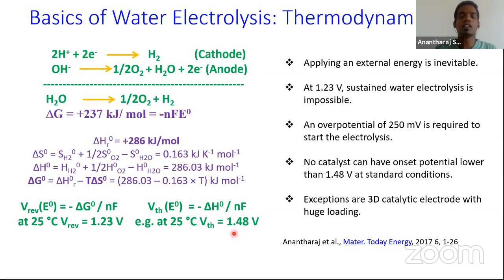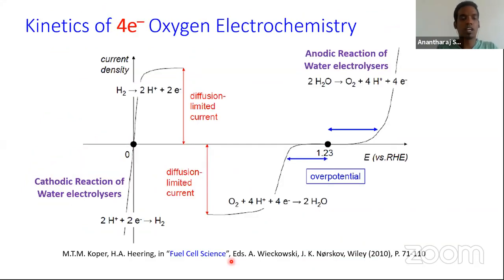So technically there is no catalyst which can split water at 1.23 volt, and additionally 250 millivolt at least as overpotential is necessary. But there are some exceptions to this condition, where the material is extremely active or has a 3D structure with a highly loaded amount of catalyst, and those catalysts have delivered exceptionally good activity where the overpotential is lower than the thermoneutral overpotential. So if you want to know more about the thermodynamics, you can refer to my review article, this one, and let's move on to the kinetics part.